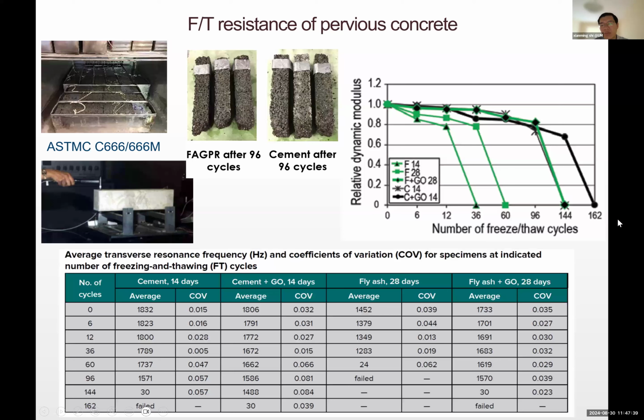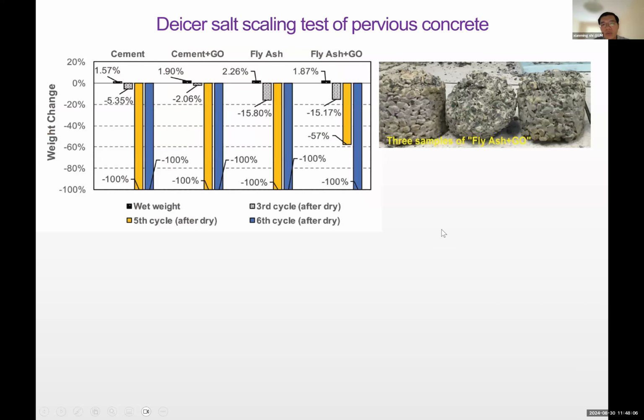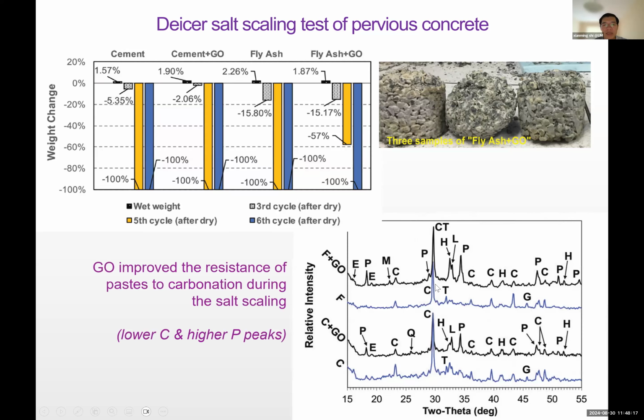But the main storyline is that with the modification of graphene oxide, the fly ash geopolymer did comparably well as the cement-based ones. Now, what about de-icing? Sorry, that one was freeze-thaw, so no de-icing involved. But again, still very harsh because they were sitting in water, and the freezing rate is very rapid, which almost never happens in the real field environment. Now, in the ice salt situation, actually the one with geopolymer and graphene oxide did better than the OPC counterpart. And there's, of course, some chemistry explanation, because the graphene oxide improved the resistance of the paste to degradation during the salt scaling. And again, I won't go into details. All these are published in ACI or other journals.